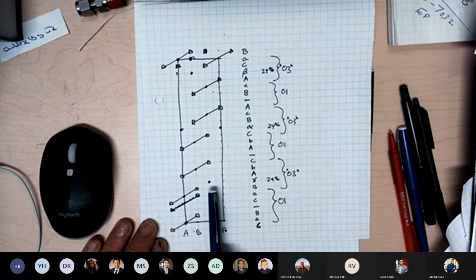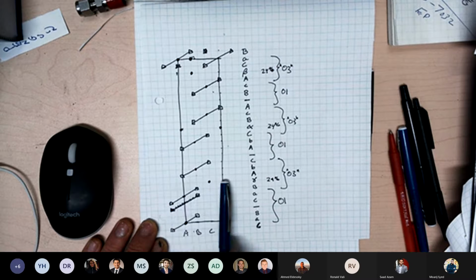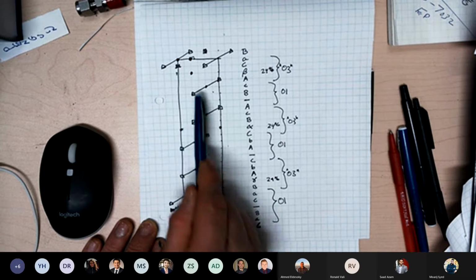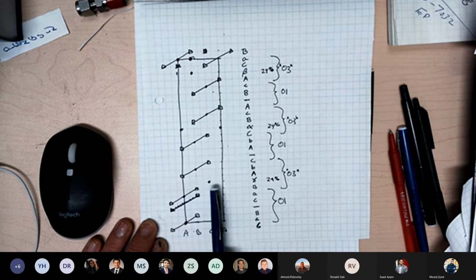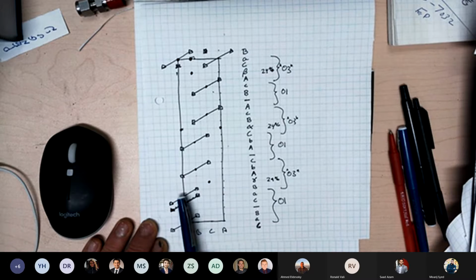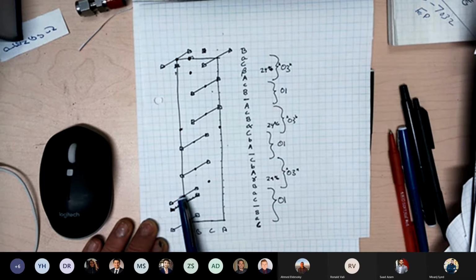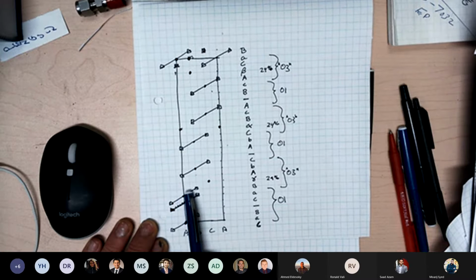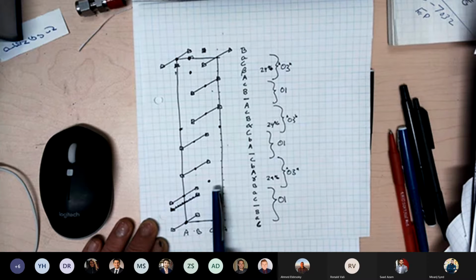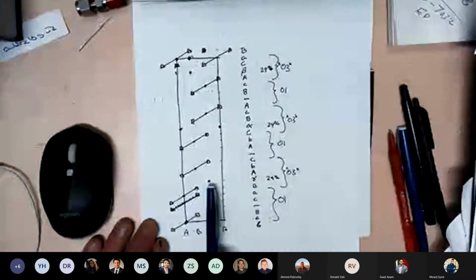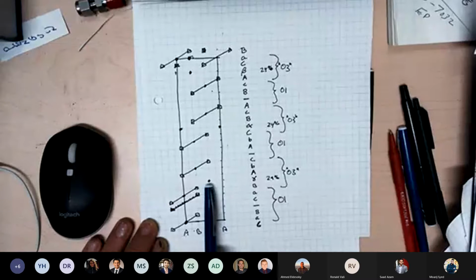And then in this structure, there's lithium in between every second pair of cobalt oxygen slabs. Those two, where the lithium is, take the O3 type of stacking, where the cobalts are shifted relative to one another. Now in this O6 structure, the lithium sites are only about a quarter filled randomly.